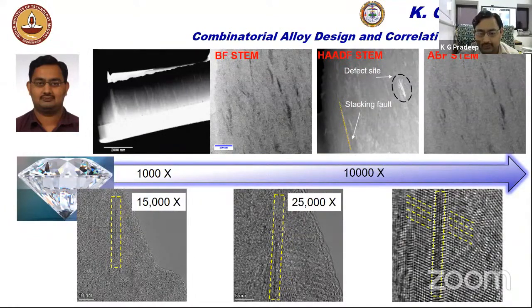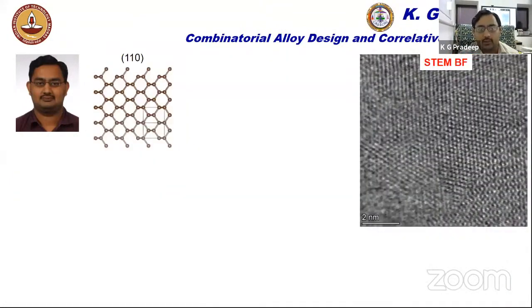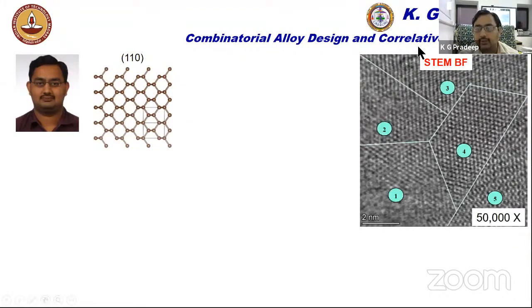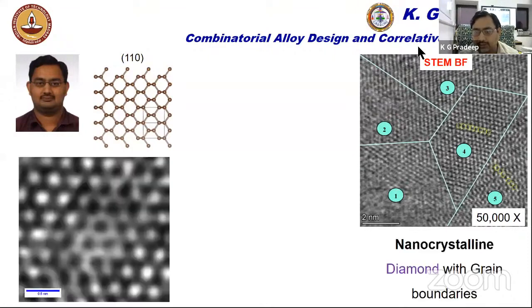If you go even higher in the same region, let's say at the same 50,000 times, then you see these nice local twin domains. And now at that similar magnification, you can distinguish this image containing a lot of local variations in orientation, meaning local segmentation. And even within these segments, you will be able to find this nicely coordinated structure, which you can now combine with the simulated, let's say, 110 orientation of a diamond film.